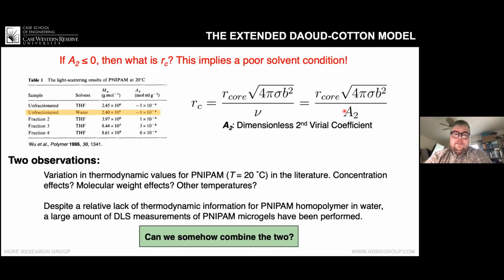So there's two observations. One is that there's variation in the thermodynamic values of PNIPAM at 20 degrees C. These could be concentration effects, molecular weight effects. It varies as a function of temperature. And also, I showed you three studies. That's about all we could find. So despite the lack of thermodynamic information for poly-NIPAM homopolymer, there are quite a few studies of DLS measurements of NIPAM microgels. So the question is, can we combine these two approaches to somehow resolve how we would calculate the transition point between these two regions?